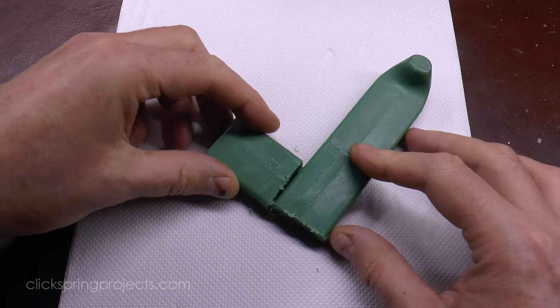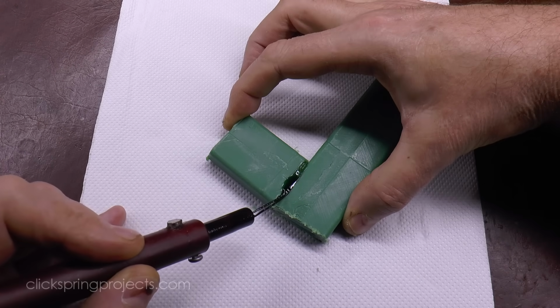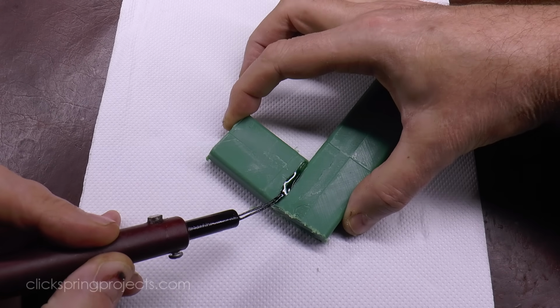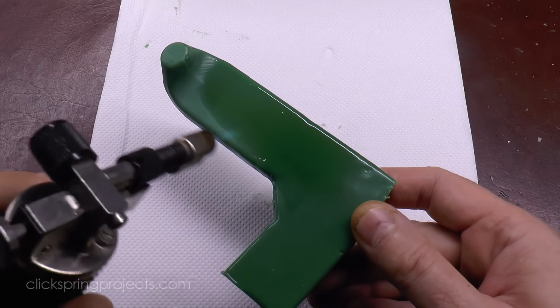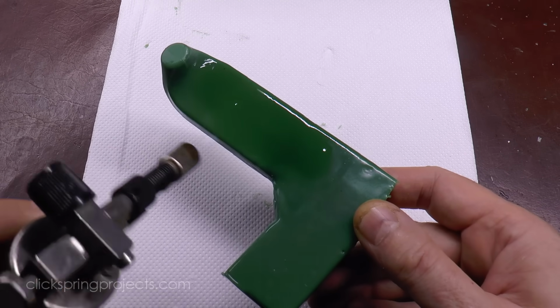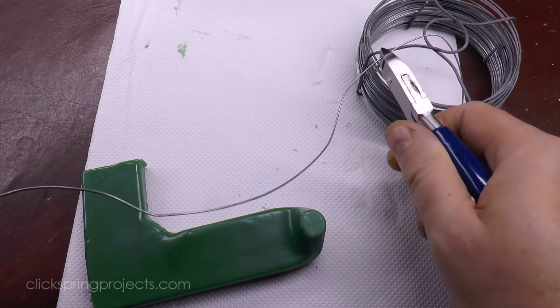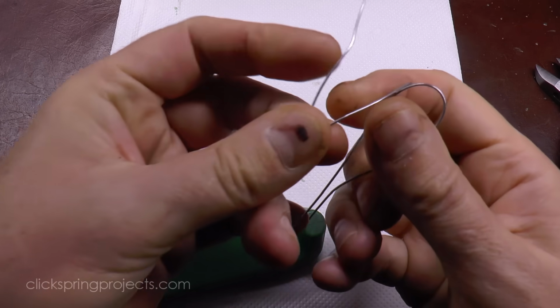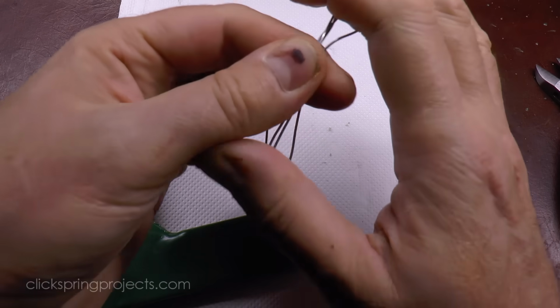In the case of the runner for this pattern, I've joined two sections together to separate the printed components and still have them fit conveniently in the slurry bucket while investing. And then I added a small amount of soft iron wire as an insert to give the join to the sprue some extra strength.